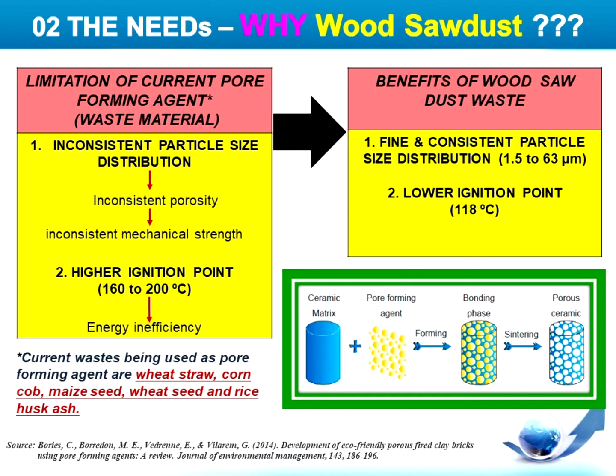Therefore, in this invention, wood sawdust has great potential as a pore-forming agent for the ceramic thermal insulator because the dust has a fine and uniform particle size distribution ranging from 1.5 to 63 micrometers. In addition, wood sawdust also has a much lower ignition point of approximately 118 degrees Celsius. Hence, a much lower firing temperature is applied to ignite the dust and eventually form pores. Subsequently, this is capable of reducing embodied energy as well as carbon footprint for the production of porous thermal insulator.